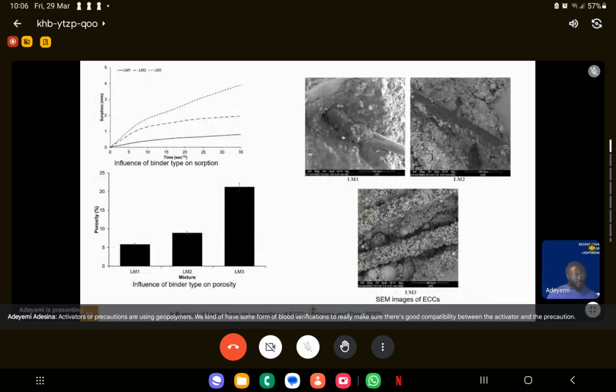And also from this test, we did other tests, which is similar to the compressive strength. We found that the more we increase the amount of fly ash, the lower the porosity, which also is reasonable to be responsible for higher absorption. But then when we look at the microstructure, what we realize again is that the thesis we made earlier was correct. The lime was only able to react with the slag, and mostly because of the presence of the calcium in the slag. Whereas there's lack of really interaction, or there's lack of geopolymerization with the fly ash particles.